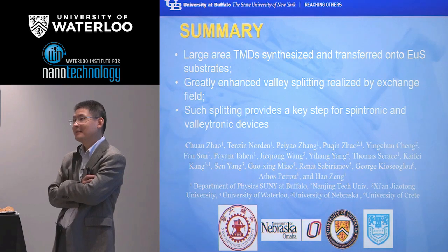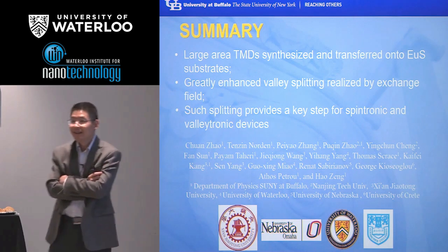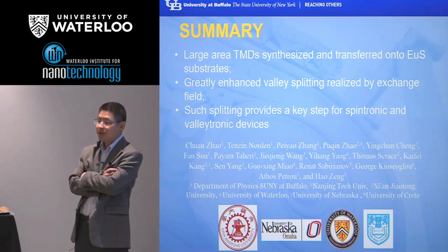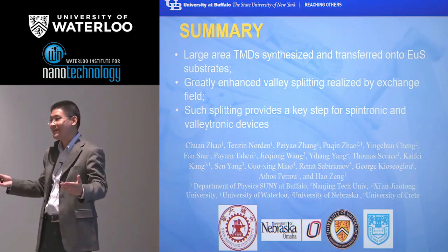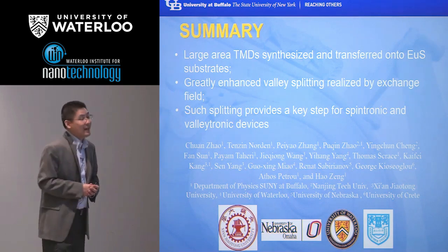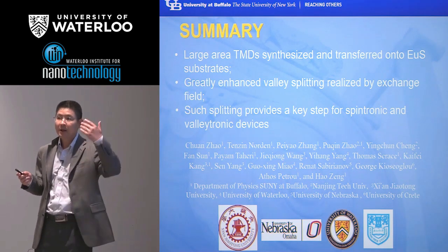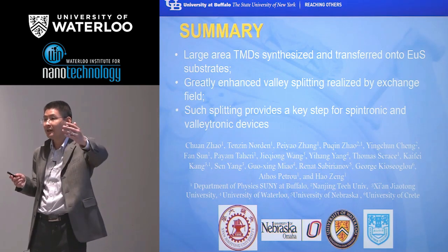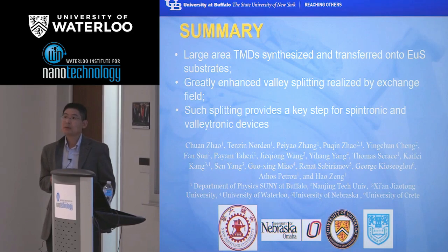With europium sulfide, that's really an interesting idea. But from a purely practical point of view, Curie temperature is killing you. Very good question. The reason we went with europium sulfide, as I mentioned, is because, first of all, it's an insulator. We do not have a lot of choices for ferromagnetic insulators. Most ferromagnets are metals, right? And so of course, we are thinking along the line of how to improve the magnetic properties of it, improve the Curie temperature, and also change the easy axis orientation of the magnetic materials, right? So you can realize this.